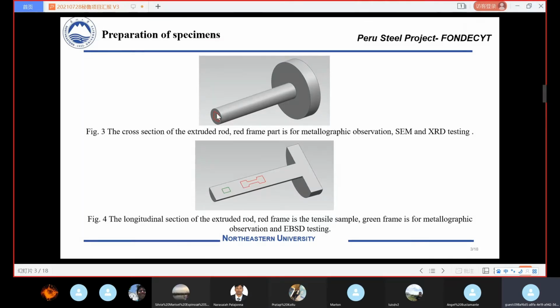Besides the cross section of the extruded rods, we also observe the microstructures along the longitudinal section of the extruded rods, which means this is the extrusion direction. This red specimen is for the tensile test, which is used to measure the mechanical properties. The loading direction is parallel to the extrusion direction. And here is a green square. This specimen is for the metallographic observation and EBSD testing, whose results will be shown in a later slide.